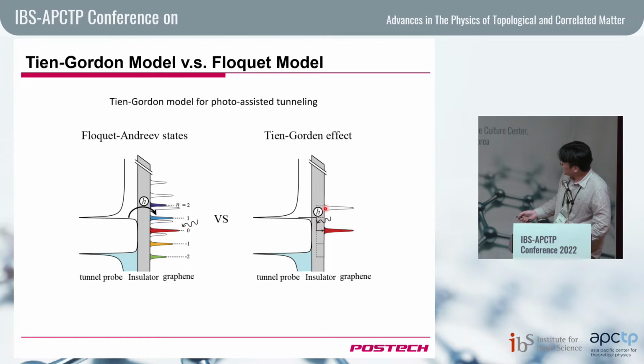So for that scenario, the electron or hole that is coupled to the light is actually the tunneling electron from superconductor to the material. In our Floquet picture, the electrons that couple to the light are the electrons inside of the graphene. So the density of states inside the graphene, in our case the Josephson junction, is replicated, and we were just observing this replicated spectral density using this tunneling probe. But if the electron that is tunneling through the barrier is coupled to the light, it can absorb or emit energy, which can result in inelastic scattering, which can give the same result.